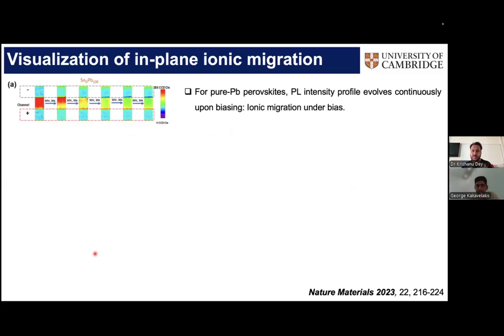So we made some two-terminal devices. So these are just not FETs, just two-terminal devices. And we measure the PL of these structures, and then we apply some voltage and then remeasure the PL. So this is how these measurements are done. So you can see for the lead-based perovskites, we initially start with a nice high PL in the channel region for perovskite. As you apply some voltage pulses and track the PL, you can see the PL starts to reduce, and it starts from one of the sides of the structure and then percolates throughout the channel region, and after several cycles of these pulse voltages, you get very low PL count. So this means that the ions are moving, creating a lot of defects, and therefore your photoluminescence intensities go down pretty significantly.